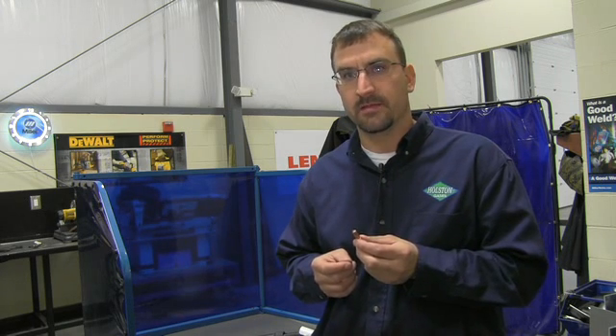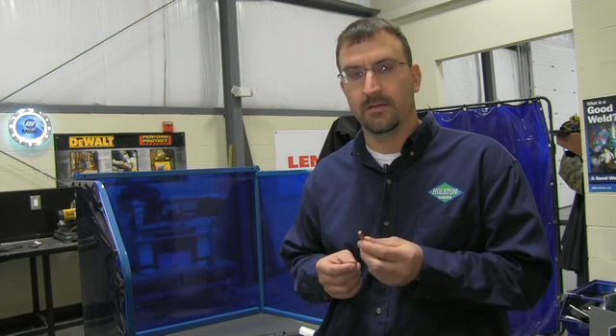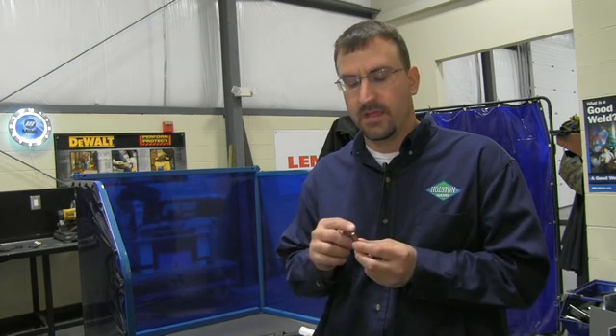You have some cheaper copper or some softer copper that's used, and so during the welding process, as the contact tip heats up, that softer copper will tend to misshape. And when this happens, it causes that wire to have room to move inside of that contact tip. And that wire is going to be bouncing back and forth, arcing back and forth on each side of the contact tip. And over not very long amount of time, this will cause arc spots inside of the contact tip, and these are rough surfaces where the wire can snag momentarily, causing it to burn back. And it doesn't take very long for this to happen.